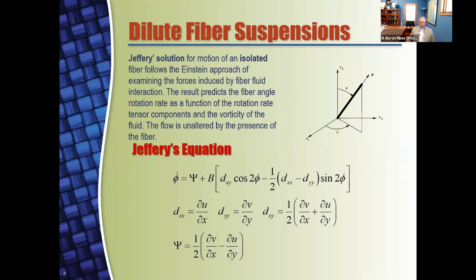And you can see Jeffery's equation here, which is expressed in terms of the deformation rate tensor, in this case planar. I've tried to make it simple for you, including the vorticity. Each of these terms describes the fluid dynamics in which the fiber finds itself. And the fiber is reacting to forces, the hydrodynamic forces in the case of water, which cause the motion of the fiber. This is the beginning point of all the work that we have today in fiber orientation and flow and the prediction of final fiber orientation in a molding simulation.